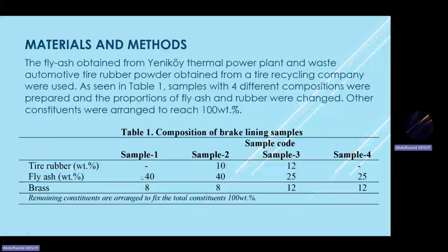As we can see, we have sample 1 and 2. They differ with the amount of tire rubber they contain. Sample 3 and 4 also have the same amount of fly ash, and sample 3 has tire rubber and sample 4 doesn't have any tire rubber. So for these samples, we will be able to observe the effect of both fly ash and tire rubber on the tribological properties of the samples.